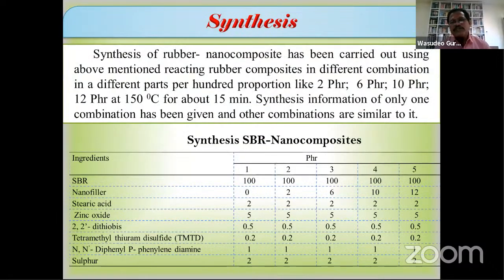So here is how to synthesize this SBR nanofiller composite material. In this table, the synthesis of SBR nanocomposite material is shown. We have taken different compositions, and here SBR in all cases is 100 gram, and the nanofiller we have changed from 0, 2, 6, 10, 12 PHR. Zinc oxide, TMTD as an accelerator, and the activator are added. After making the compositions shown in the table, we can prepare the five different rubber sheets.